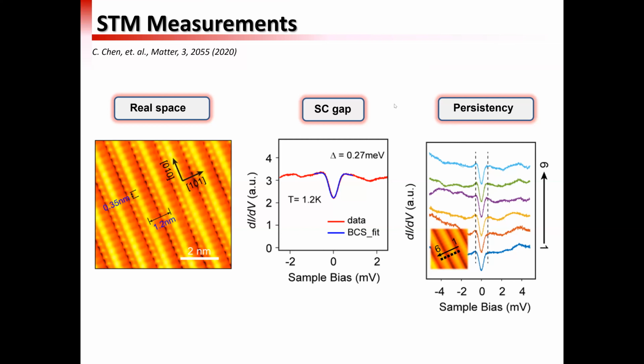That's very good for our ARPES measurement. Otherwise, because ARPES doesn't have the resolution of the STM, typically in this measurement we have only 10 micron resolution. So if the material property is inhomogeneous on the surface, then ARPES can only measure the average signal. But in this case, we're assured that the surface is pretty homogeneous.